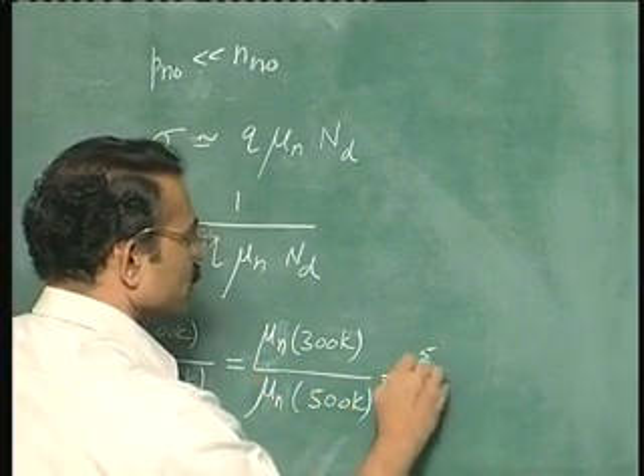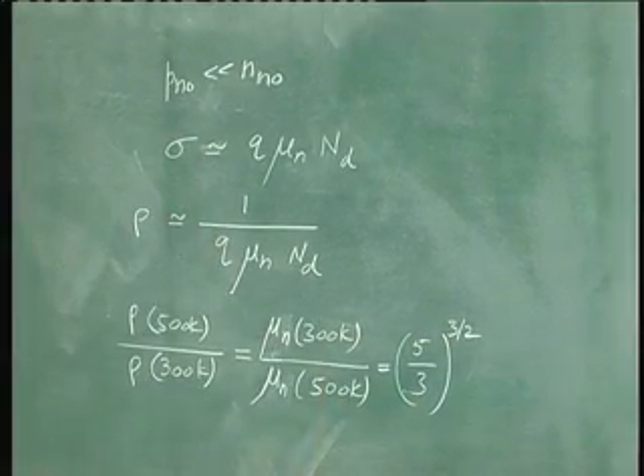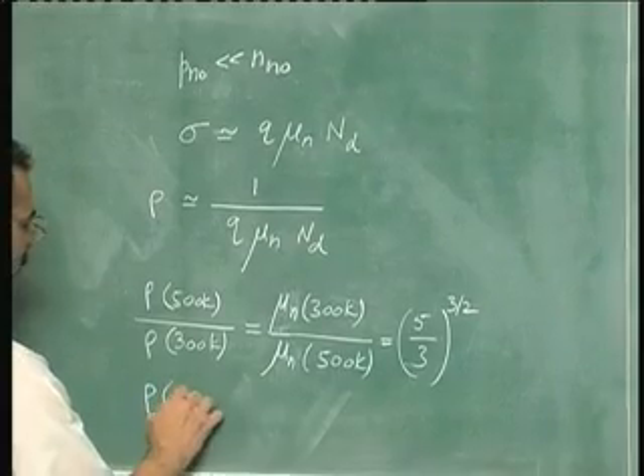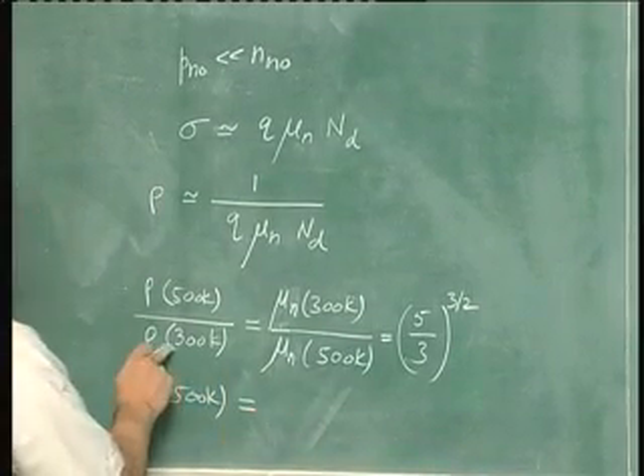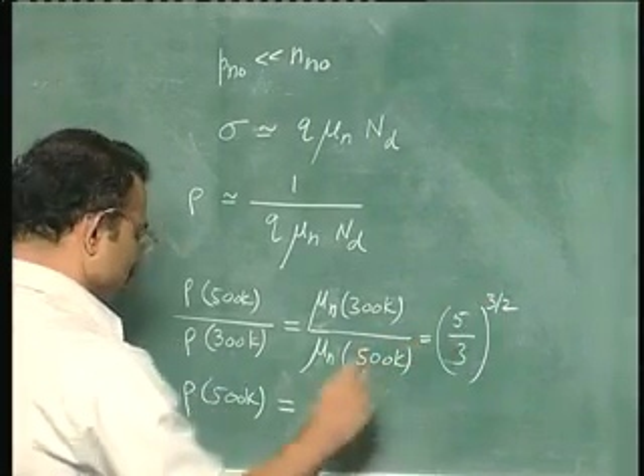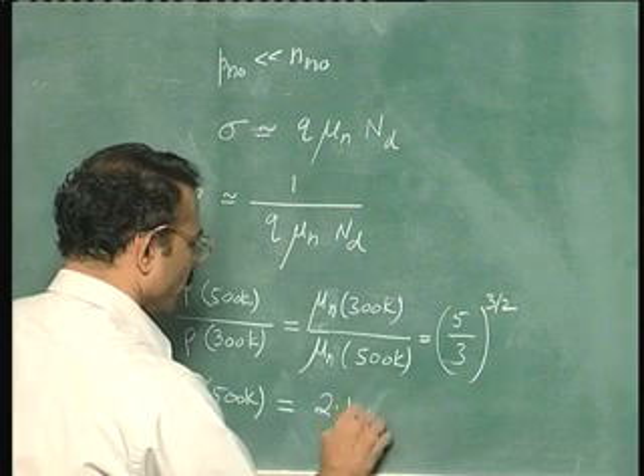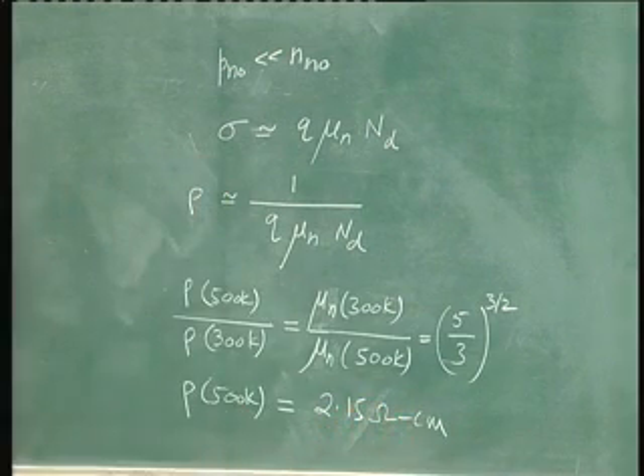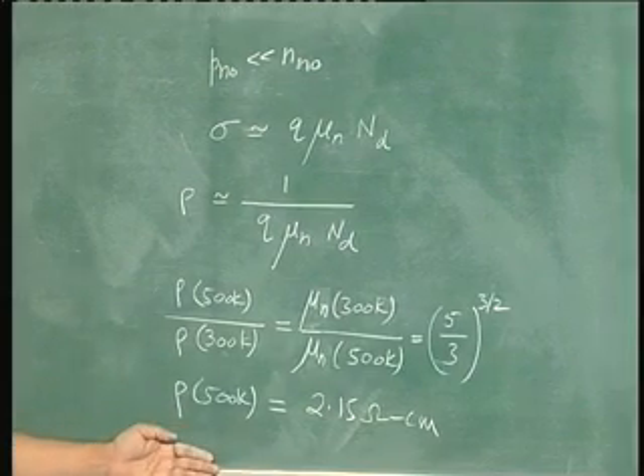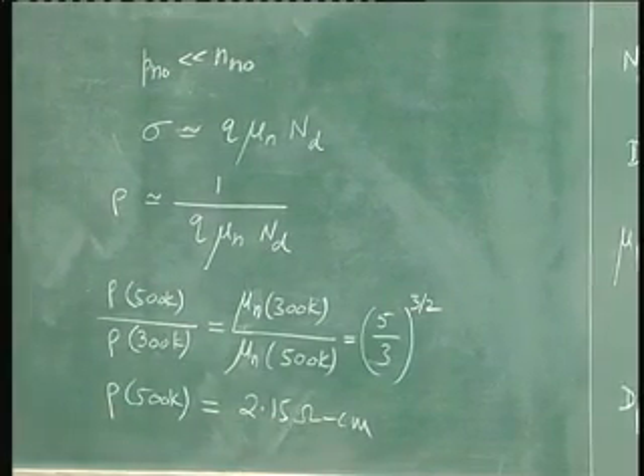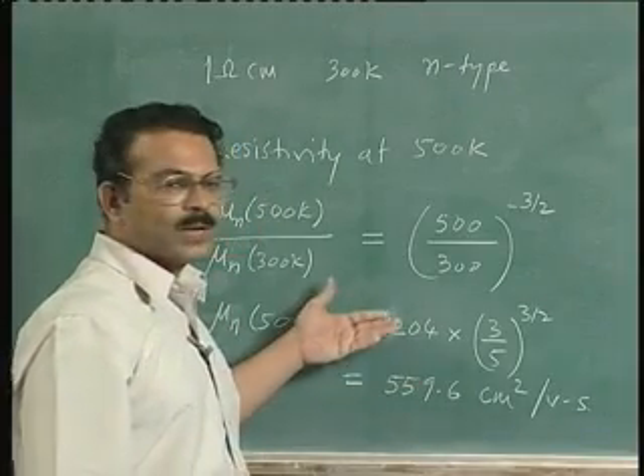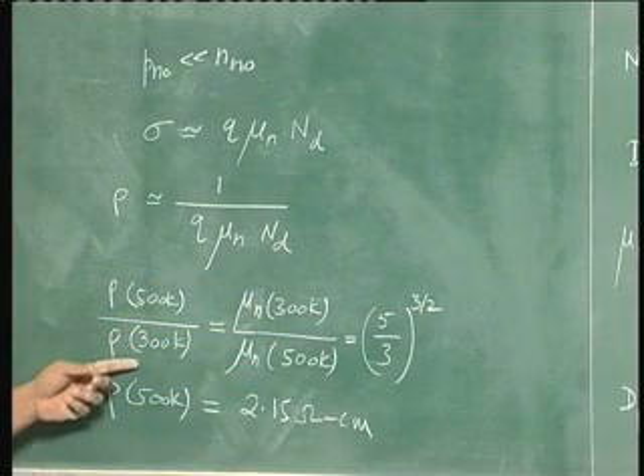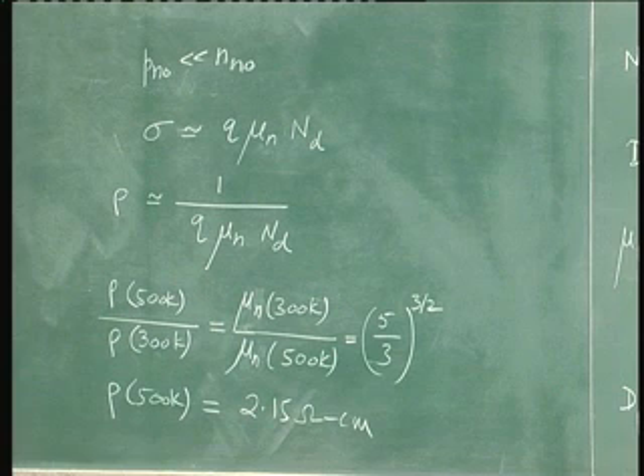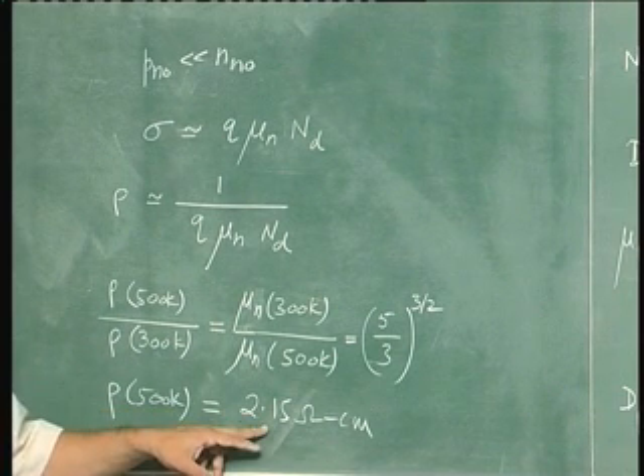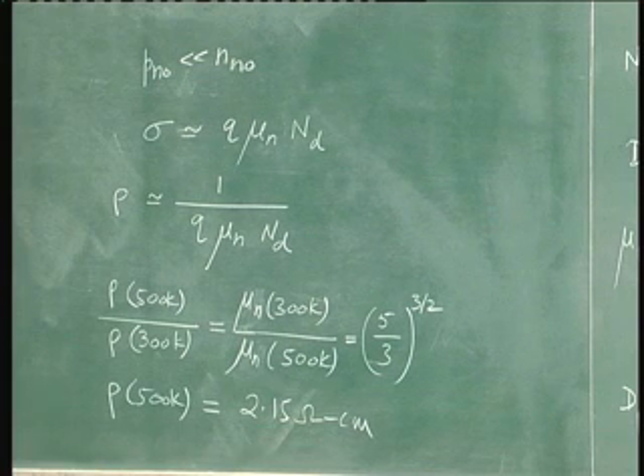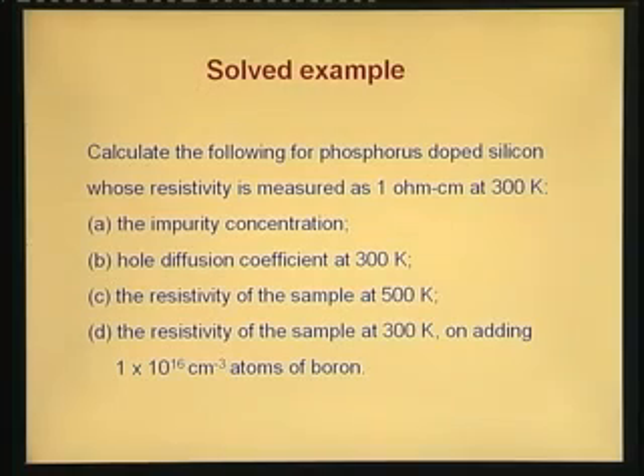And this is equal to 5 by 3 whole power 3 by 2. And the result therefore is resistivity at 500 K is equal to 300 K resistivity, which is 1 ohm centimeter, multiplied by this term, and the result would be 2.15 ohm centimeter. So this is the way one can find out the resistivity at a different, higher temperature. So you can find out the mobility at a higher temperature and find out the resistivity, but since we already know the resistivity at lower temperature, it is easier to write it in this simplified form, and then get the resistivity. So you see at higher temperature actually the resistivity has increased, because of the fall in mobility.